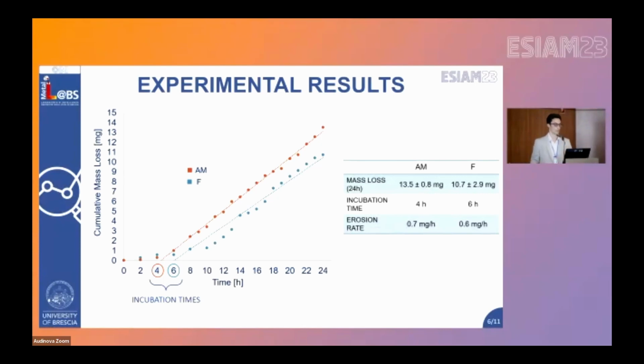We had to reach the limit of 24 hours of the standard to even have a 13 milligram loss of material for the additive and 11 for the forged. So both materials were extremely resistant to erosion.